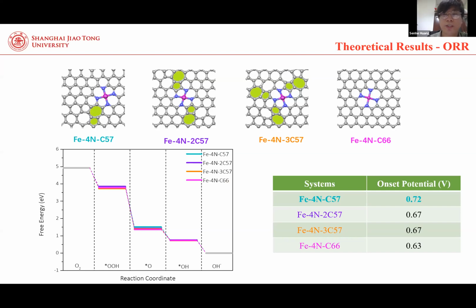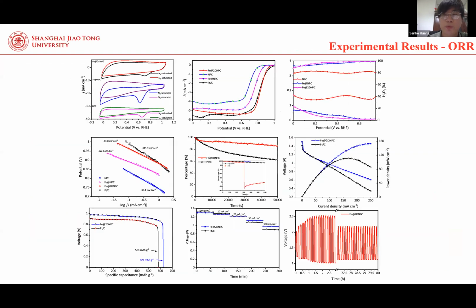The differential charge density of this system is also studied. The differential charge density can show the interaction between the surface and the adsorption species. From theoretical results, we can predict the potential application of this catalyst in oxygen reduction. Then we also studied the experimental characterization of oxygen reduction testing.